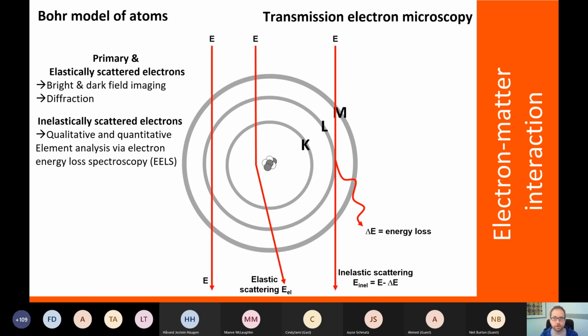We can also use those electrons that actually go through the sample. They don't change their path, but they lose energy. So these are called inelastically scattered electrons. And this is a very powerful technique for qualitative and quantitative element analysis via something called electron energy loss spectroscopy. We not only can get chemical information, but also nearest neighbor information. There's an infinite amount of possibilities using electron energy loss spectroscopy to go very deep into material behavior. And of course, we have secondary electrons and X-rays transmitted, and I will very briefly talk about X-ray analysis in a TEM in a minute.